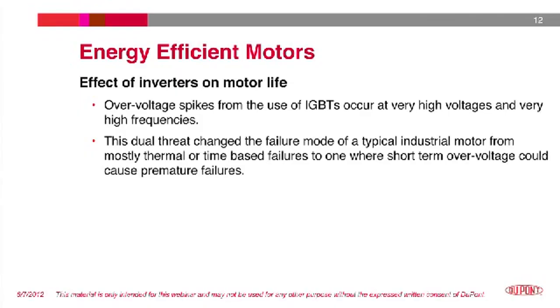Investigation into the cause of failures identified overvoltage spikes caused by the use of the IGBTs in the inverter systems. These spikes were both at very high voltages versus the system voltage of the equipment and at very high frequencies. This dual threat changed the typical motor failure from a purely thermal failure to one caused by a short-term overvoltage. The industry has recognized the need to provide new test methods for addressing these problems.